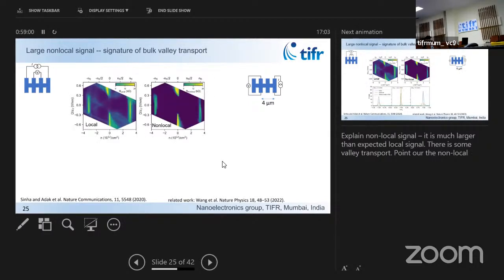So we do this measurement: this is local resistance, this is non-local resistance, and the non-local resistance is large precisely where the gaps are large. And that's precisely the location in energy where Berry curvature is large. That's why you see a large non-local signal. And everywhere else, in the middle of the band, you have lots of electronic states, but no non-local signal because there's very, very feeble Berry curvature.